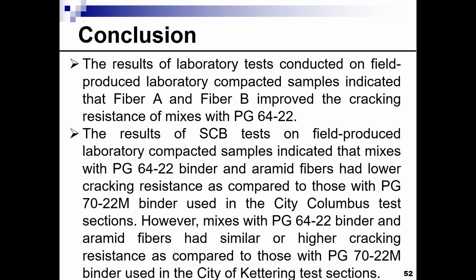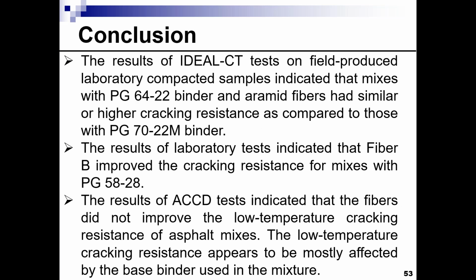Now, a very important thing, and I would like to note, is that although we're using a 70-22 and both binders in both projects met the specification of the 70-22M, those are coming from two different producers, so we're expecting differences in performance even between the same polymer modified mix. So this is a note that we want to make sure that we have.